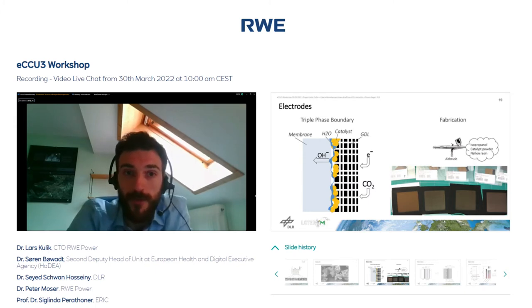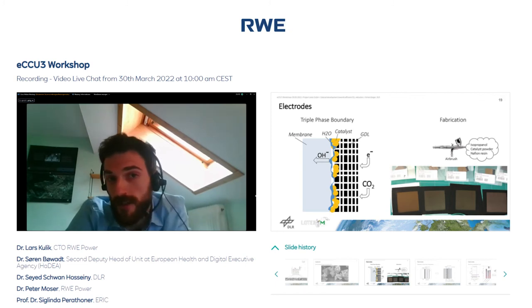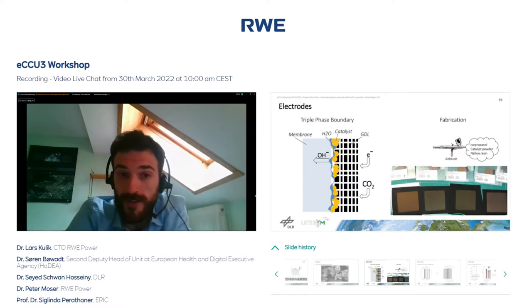So the first one is that electrons need to be transferred to the catalyst, which is shown here in orange, by the gas diffusion electrodes, usually an electronically conductive material like carbon. But at the same time, it needs to be also porous so that gas, our CO2 gas, can reach the catalyst as well. So usually they have some porous structure here. And then we also need to have an ionic conductivity. So usually H plus needs to reach the catalyst, or in this case, OH minus needs to leave the catalyst.